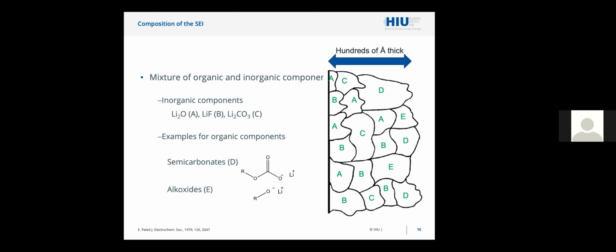I'm sorry, there is some overlapping. And the inorganic components are definitely very important. These are usually lithium oxide, lithium fluoride, lithium carbonate, which can be formed by the decomposition of both the salt anion as well as the solvents. And then there is also a certain fraction of organic components like semicarbonates or alkoxides. And there are also some polymeric components formed by the decomposition of the solvent, which altogether guarantee this optimal performance, which we see in commercial lithium-ion batteries. Okay.